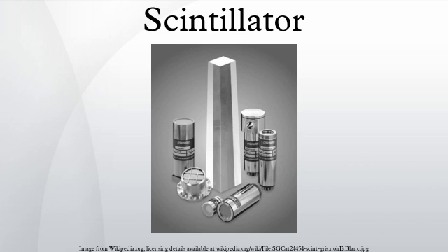Glasses. The most common glass scintillators are cerium-activated lithium or boron silicates. Since both lithium and boron have large neutron cross-sections, glass detectors are particularly well suited to the detection of thermal neutrons. Lithium is more widely used than boron since it has a greater energy release on capturing a neutron and therefore greater light output. Glass scintillators are however sensitive to electrons and gamma rays as well. Being very robust, they are also well suited to harsh environmental conditions. Their response time is approximately 10 nanoseconds, their light output is however low, typically approximately 30% of that of anthracene.